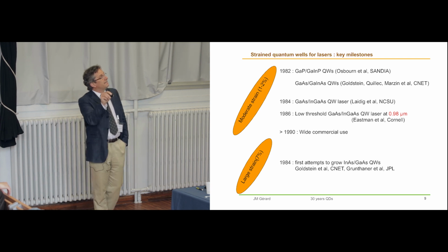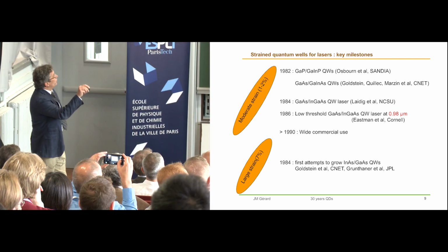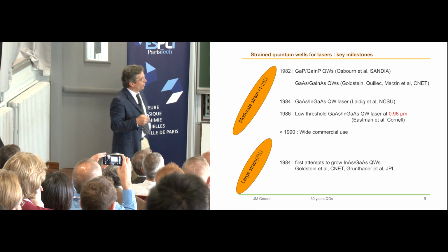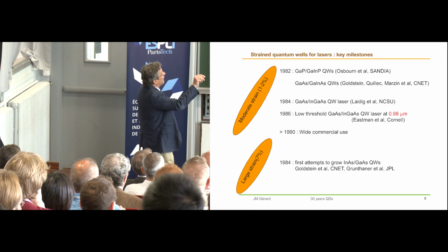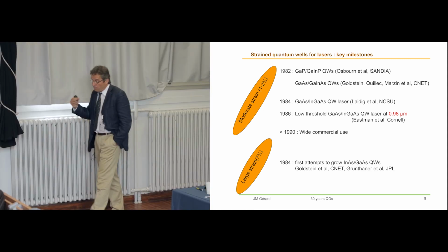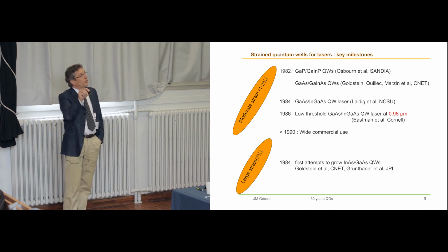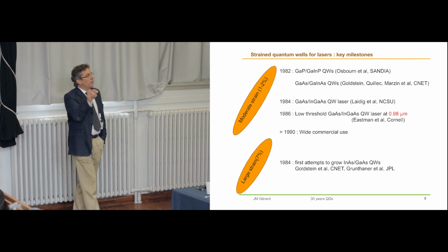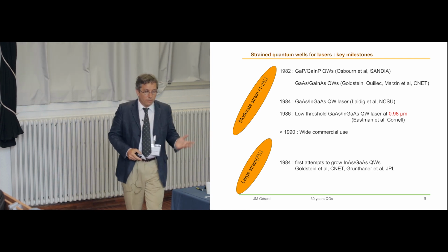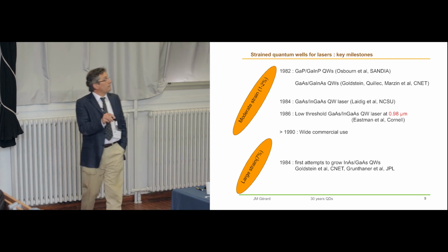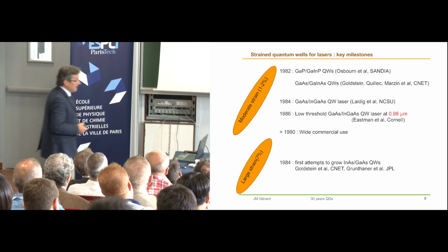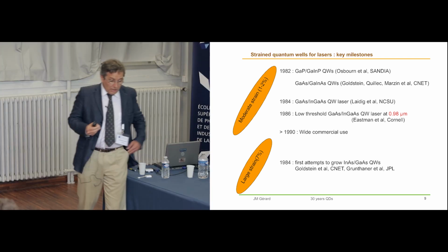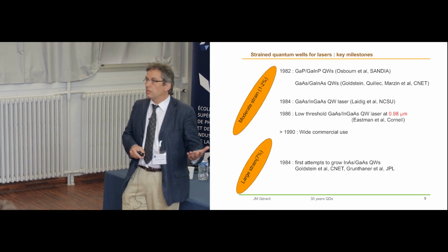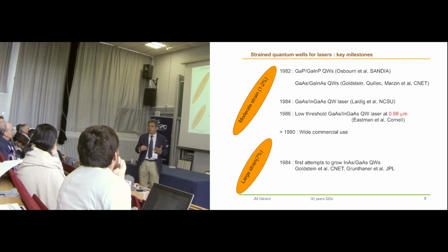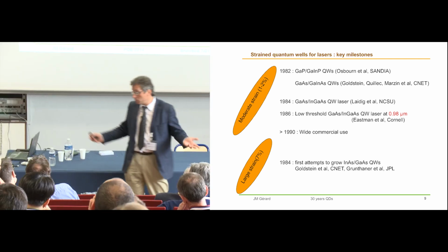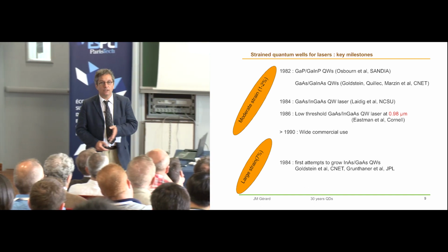So they prepared nice strained quantum wells. Slightly later, two groups in the States demonstrated the first strained quantum well lasers, including lasers at 0.98 micrometers for the pumping of erbium-doped fibers. So a very important result here. And very fast, again, strained quantum well lasers became the dominant product within laser diodes. In 84, people at CNET, as well as at JPL, wondered how far this approach could go. And so they decided to put as much strain as possible in the system. So they played with indium arsenide on gallium arsenide.